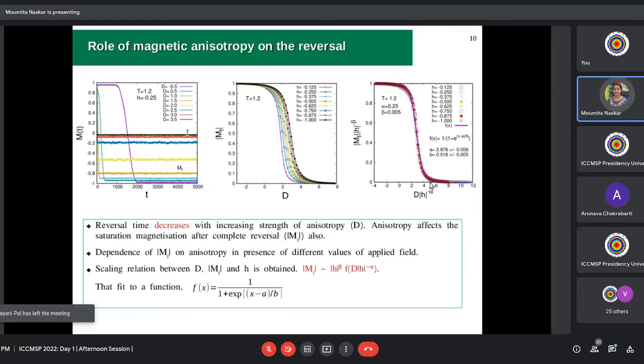But as we increase D and in the large limit of positive D, the magnetization becomes 0. It immediately seems that there is no magnetic ordering, but this is actually not true, because here the system possesses a different kind of magnetic ordering, in a direction perpendicular to the z-axis, which is basically influenced by anisotropy, not by the external field.